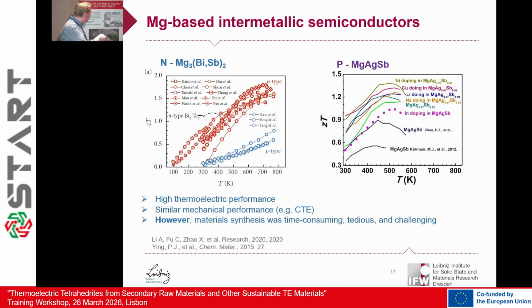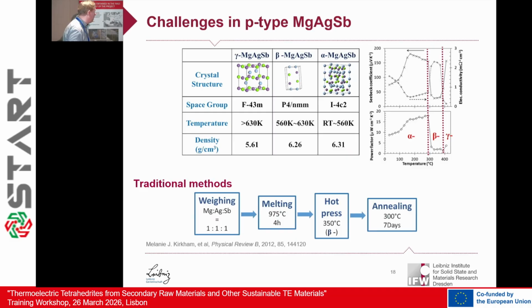The performance of the P-type material is rather moderate. We have done some improvements, but the P-type material is a low performer, I would say, but it's okay. Therefore, we decided to take the P-type magnesium silver antimonide. There are some issues about phase transitions, which I will also shortly address. But this combination could be used, for example, for thermoelectric cooling, but also for low-temperature waste heat recovery.